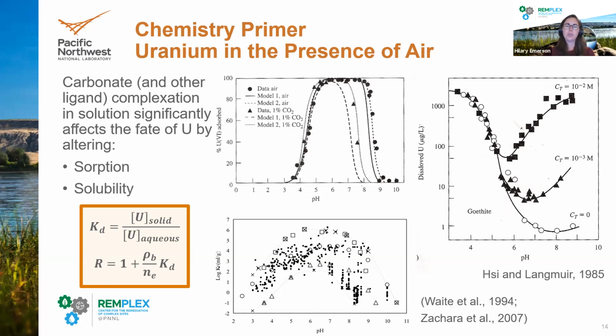So as an example, the figure on the left shows uranium sorption with respect to pH. And you can see that as the carbon dioxide concentration increases, you see a decrease in sorption. And then we see a similar phenomenon in the figure on the right, except that we're looking at the dissolved uranium with respect to pH. But you can also see that uranium in the aqueous phase increases because it's not sorbing as the pH increases.